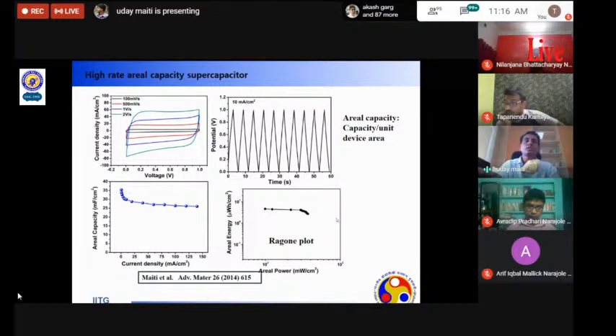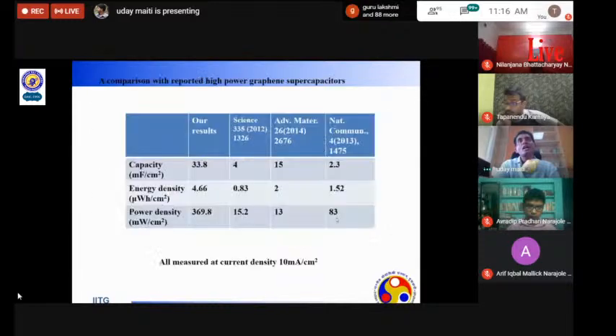And the areal capacitance is also very good. And with the increase of current density, you see that at 150, at this rate, if we charge or discharge, it still maintains a good capacitance. So it means that this is good for ultra fast charging of the capacitors. These are some metrics we have compared with other very excellent papers.